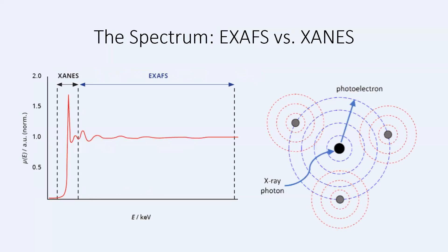EXAFS is a subset of X-ray absorption spectroscopy corresponding to the oscillating part of the absorption spectrum to the right of the absorption edge, which appears like a sharp peak. Typically, EXAFS experiments start about 50 eV above the edge and may extend as far as a kiloelectron volt above the edge. Mathematical analysis of this region of the EXAFS spectra may reveal structural information and coordination spheres about an atom of focus.